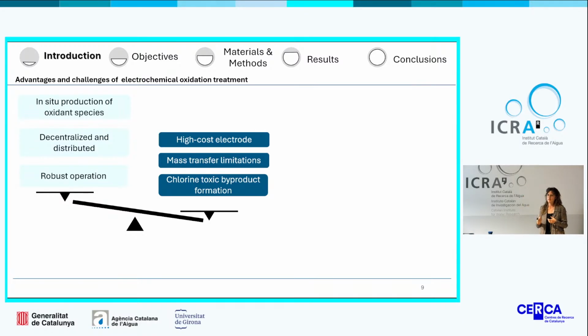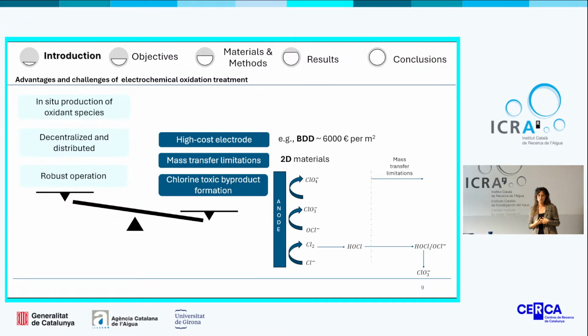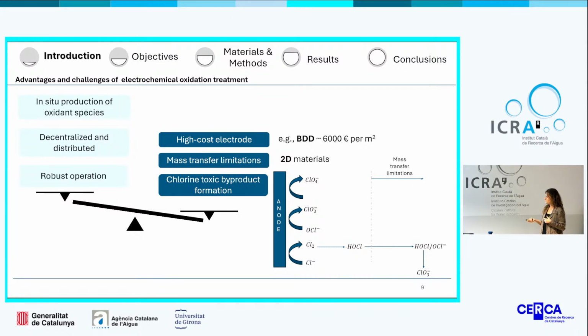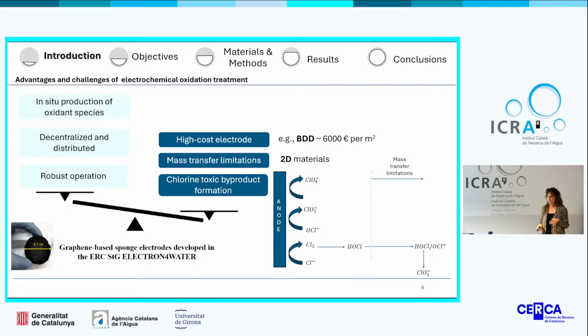On the other hand, they present some disadvantages, as for example, the high cost of the electrode, especially in the most commonly used anodes such as boron-doped diamond. Also, the mass transfer limitations with 2D materials, and the toxic chlorine byproduct formation, which usually occurs in water matrices with a high concentration of chloride, which is indirectly oxidized into chlorine, and with the organic matter can produce chlorate and perchlorate, which are toxic byproducts. For that reason, to overcome all these limitations, in our research work we designed a 3D graphene-based sponge electrode, which is totally inert to chlorine formation and really cost-effective.